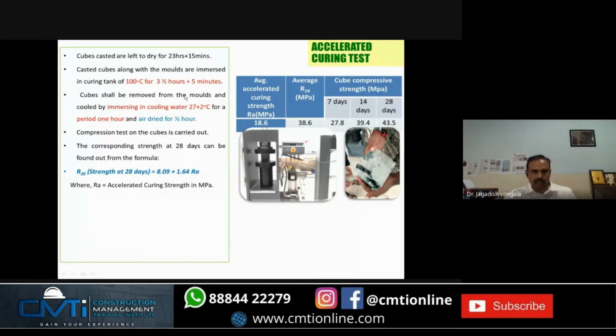Next day, the bottom plate of the mold you remove, and then these cubes with the mold itself, you place in the curing tank. Sorry, you will boil it at 100 degrees centigrade for 3.5 hours, and then remove the molds after the boiling, and cool it in water and then air dry. Then you test it. This is the accelerated projected 28 day strength based on the accelerated curing strength.